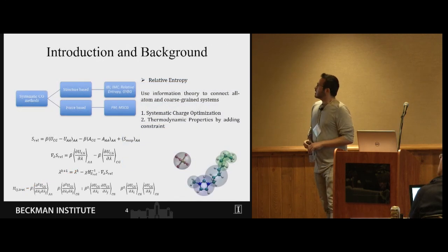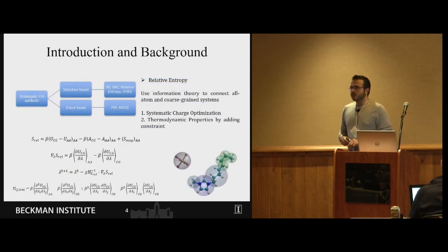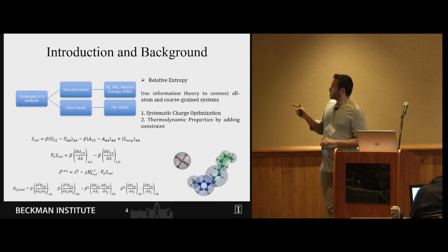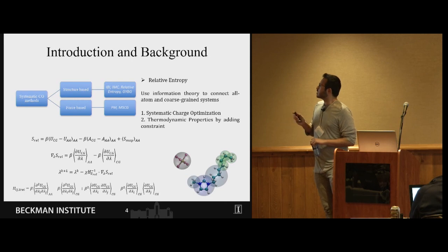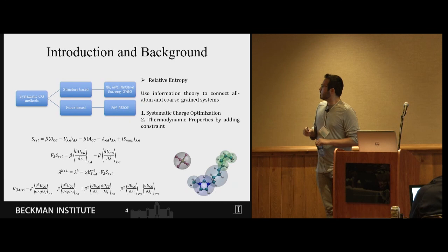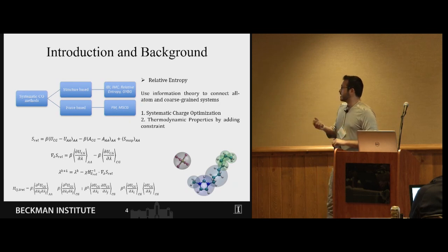In this study when I'm talking about coarse-graining I'm specifically talking about systematic coarse-graining which has two different branches including structure-based and force matching. In structure-based we usually try to retrieve or reproduce the structure of the all atom system and in the second one as the name suggests we try to reproduce the force on each bead of the system.